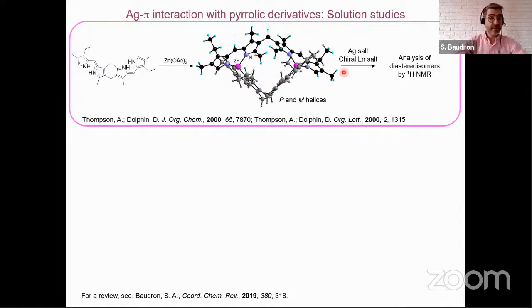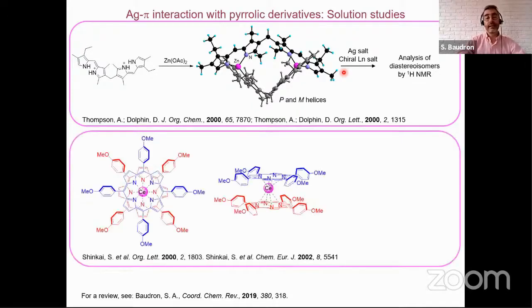Another example of a solution study that is worth highlighting is the elegant result by the group of Seiji Shinkai, where they investigated the assembly of this double-decker cerium porphyrin system, where you have two porphyrins sandwiching the cerium-4 cation, and they investigated the assembly with silver 1 salts. What they observed by NMR, Raman, and UV-visible spectroscopies is that indeed there was an interaction of a silver cation to the beta-pyrrolic carbon-carbon bond in this system. So while there were those solution studies, in terms of observation in the crystalline state, this was way more limited at the time we studied this work.